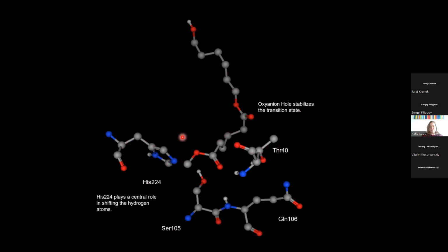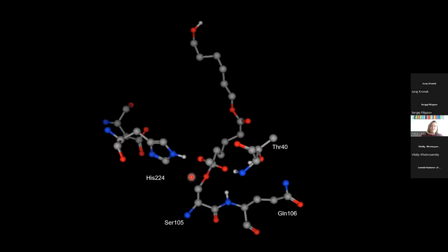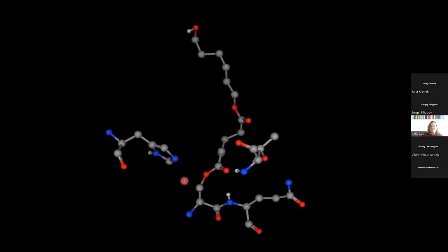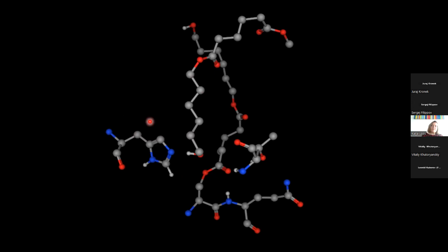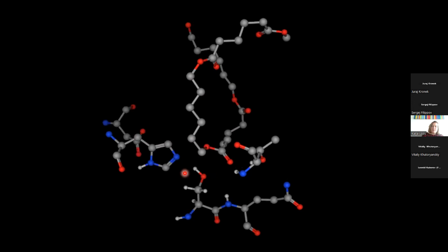So if you now want to synthesize a polyester and you use a hydroxy acid, so here you have the hydroxy group, here you have the acid group. And if it's going well, then the acid group goes down first. And then you form a transition state, and you saw that the histidine abstracted the proton. And if it goes in the right direction that you want, you form a covalent bond. And if you come down with your second monomer, then it goes down with the alcohol group. You form again a transition state and a covalent bond, which is released. And then the whole chain is pulled up so that the next acid group is down, and you repeat that.